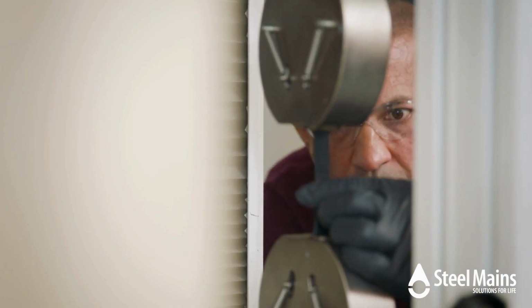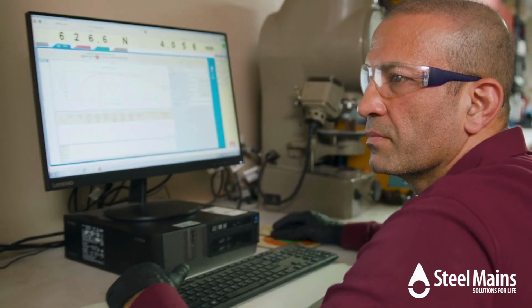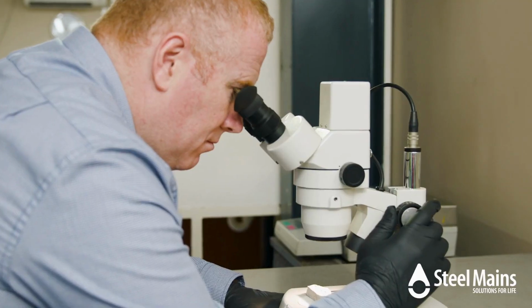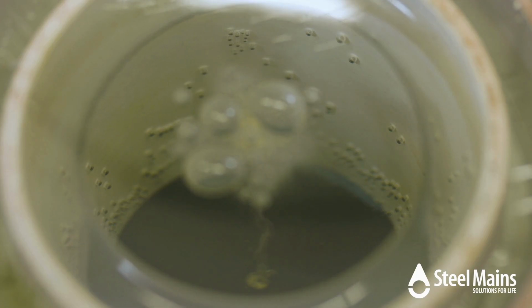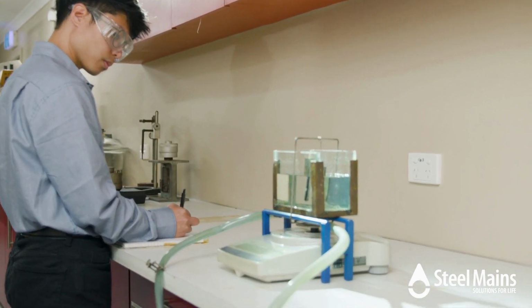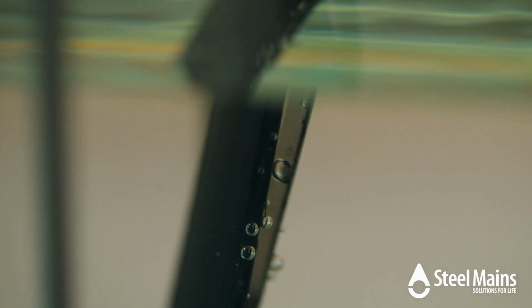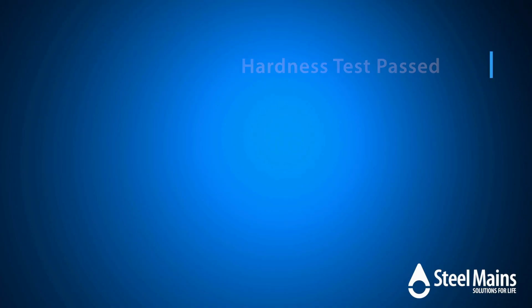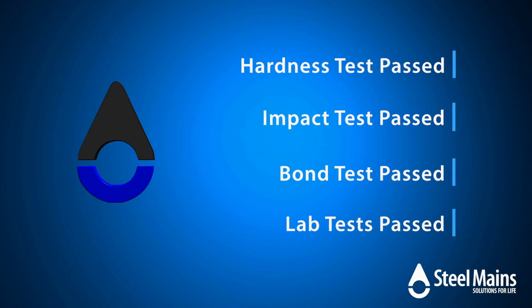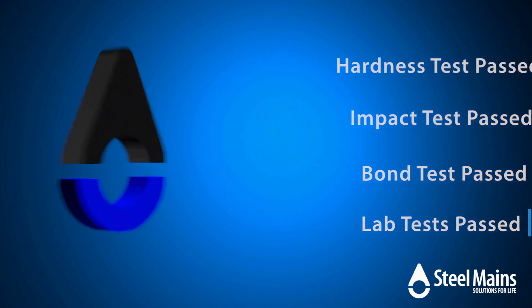Results show minimal change from original supplied properties. Thermal stability requirements are still met. In practical terms, the coating today performs almost identically to the day it was manufactured and installed in 1978. After almost half a century in service, the results are clear. Excellent adhesion, stable mechanical properties, no evidence of corrosion, no reported failures.